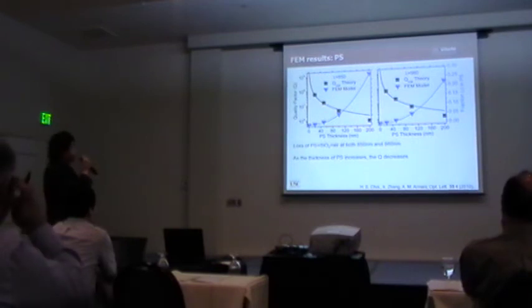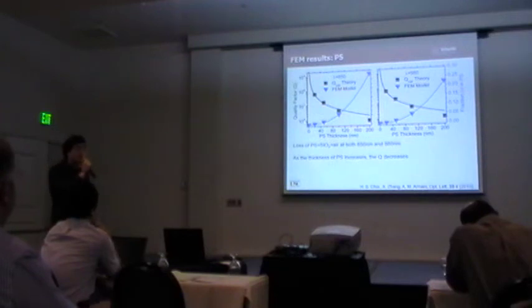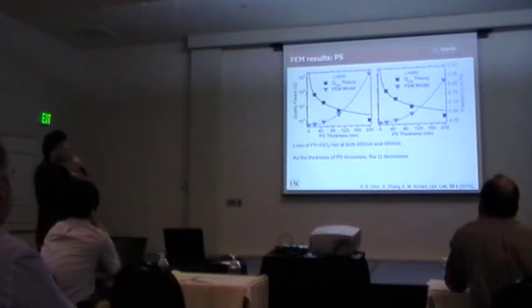This slide shows the FEM results for polystyrene hybrid devices. The same explanation goes here as for PMMA hybrid devices. One difference is that, as the refractive index of polystyrene is higher than PMMA, there will be a higher percent of field residing in the polystyrene layer compared to the PMMA layer at the same coating thickness. To summarize, the loss of polystyrene is higher than silica and air at both wavelengths. As the thickness of polystyrene increases, the Q decreases.